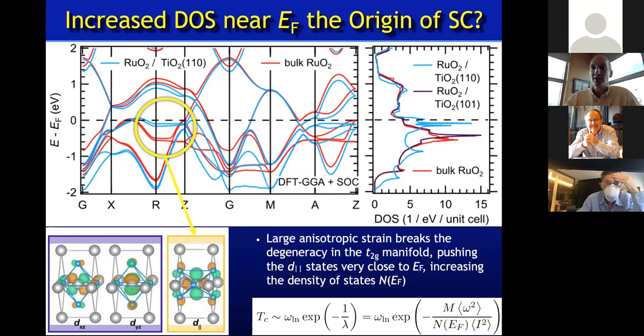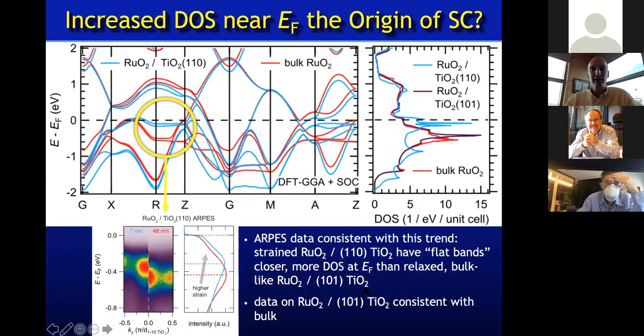So from a theory perspective, it looks like it's taking what would be a degeneracy among the T2G levels, which you heard about again from Antoine Georges earlier, and lifts that degeneracy and pushes from where bulk should have its peak in its density of states, pushes them towards the Fermi level, which you would expect to have an improvement in TC just from looking at this standard superconductivity theory.